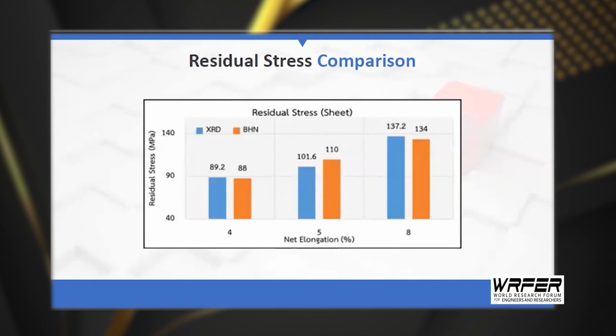Sir, you have 2 minutes to conclude, please. The average residual stress values measured by the BHN system were then compared with the residual stress values from the XRD technique. It's noted that the highest error was found at 5% elongation. This may be due to the fact that using the linear regression calculation, or maybe the pulling control is quite difficult. However, the measurement accuracy of the proposed system is 96.02% on average. Therefore, it can be said that a non-destructive residual stress tester based on the BHN technique can be used to measure residual stress accurately.